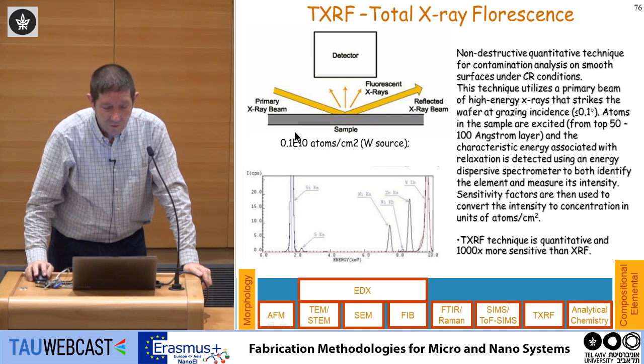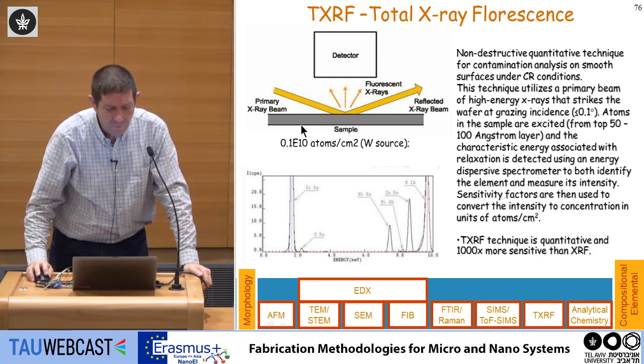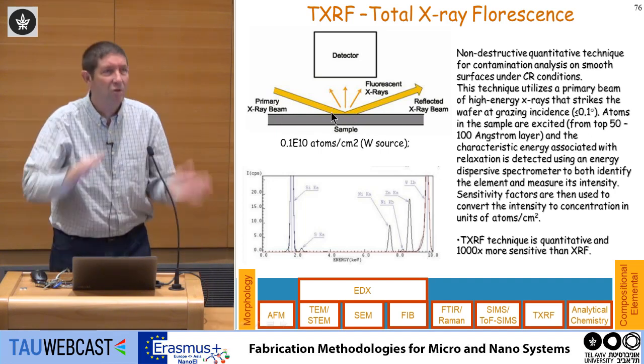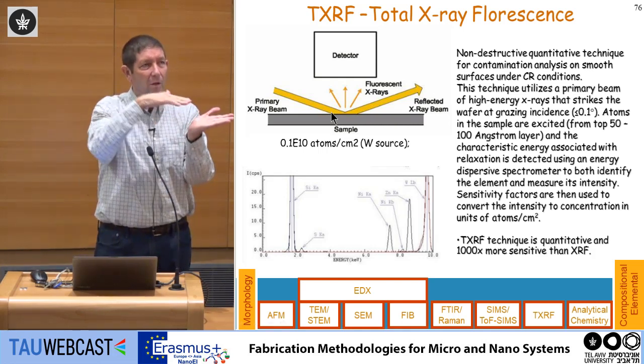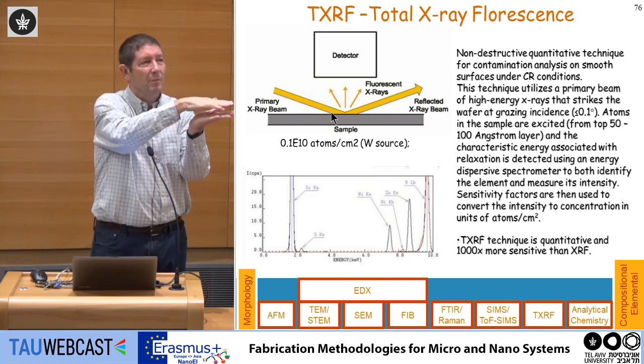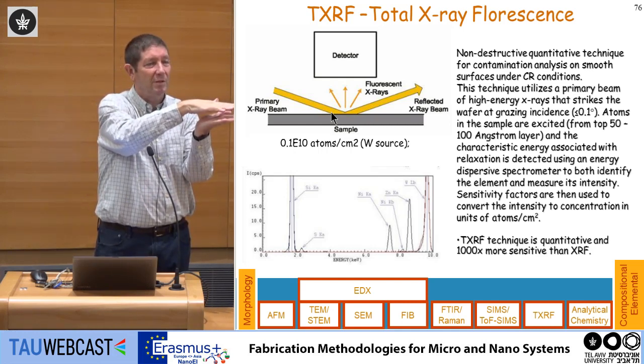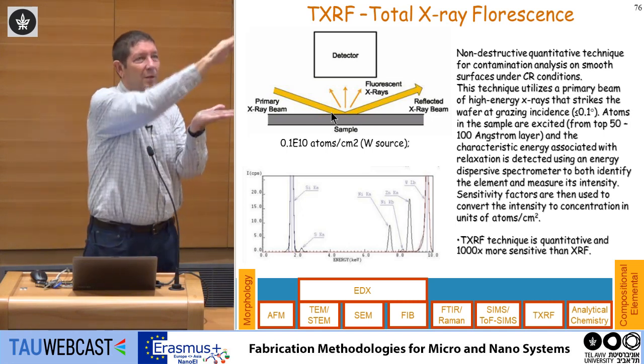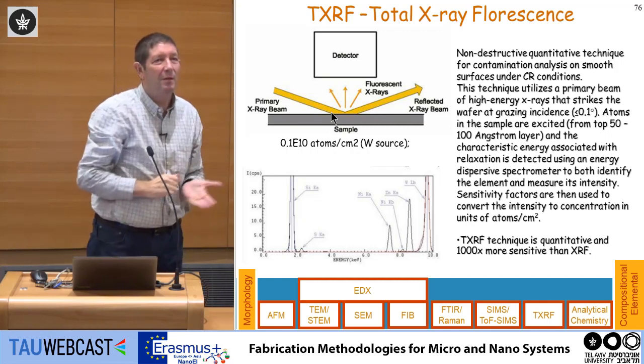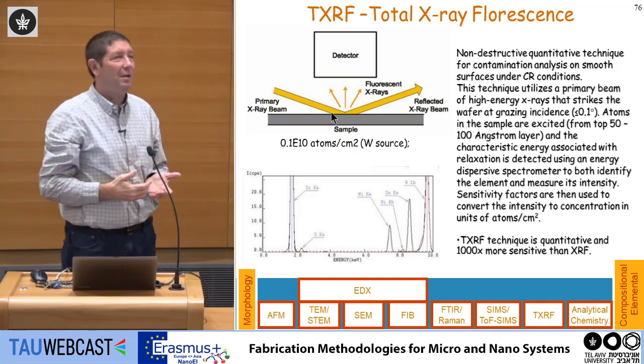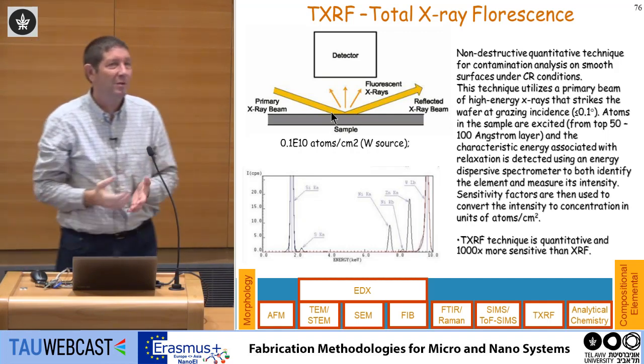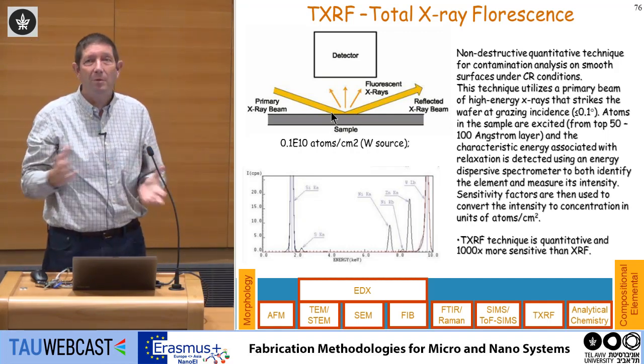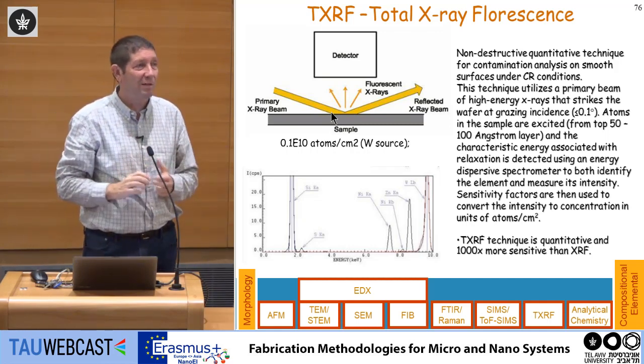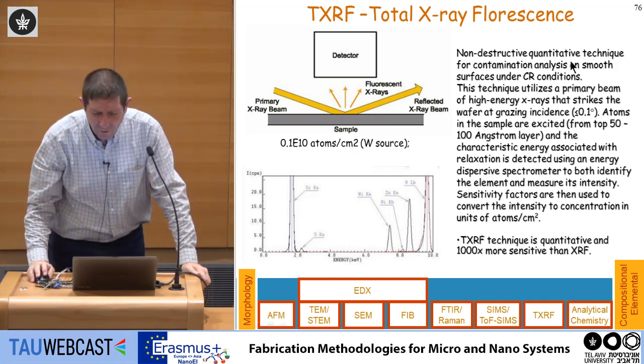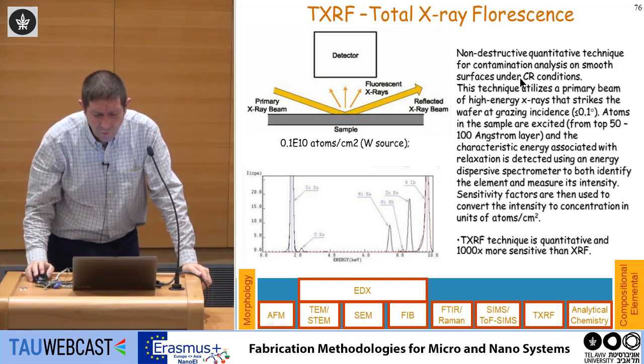Now, total XRF is a technique where, if you have a thin film and you are shooting the X-ray beam at a very shallow angle, when the beam is going into the film, you are below the critical angle. So you have total reflection inside, which means instead of just one interaction, the beam is going inside and you have many, many more interactions. So you enhance the excitation. There are two methods which are common today. One is just regular XRF, which you can apply for powder and for non-flat surfaces. But for flat surfaces, you can do TXRF. It's a non-destructive quantitative technique for contamination analysis on smooth surfaces.